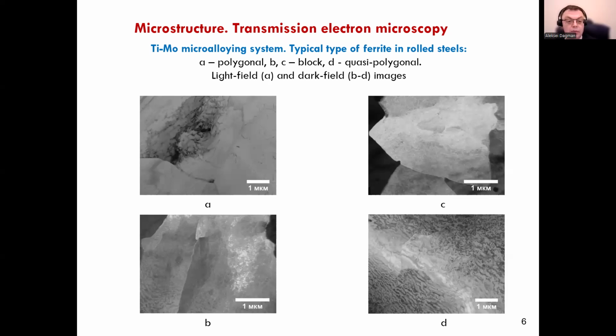In titanium molybdenum microalloying systems, the ferritic matrix is basically two components and consists of ferrites of two morphological types, block CF and polygonal PF, with the exception of the steel of vanadium molybdenum microalloying system. In steel samples containing titanium and molybdenum, the proportion of polygonal ferrite prevails, figure A, and with a low carbon content, it's higher, up to 17%. The grain size ranges from units of micrometers to average 10 microns. Individual grains exceed 20 microns.